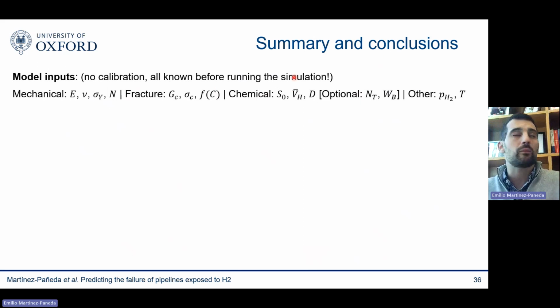Then we need the stress-free solubility, which you can get from a permeation experiment, and the partial molar volume. This is well known. The diffusion coefficient could be lattice or apparent diffusion coefficient. Optionally, if you want to resolve the traps, trap binding energy and density, these do not matter much in this application, and we can get them from TDS analysis. And then, of course, you need other things like the pressure from the environment and the temperature.